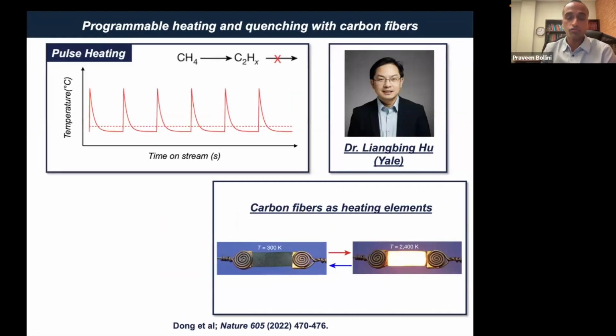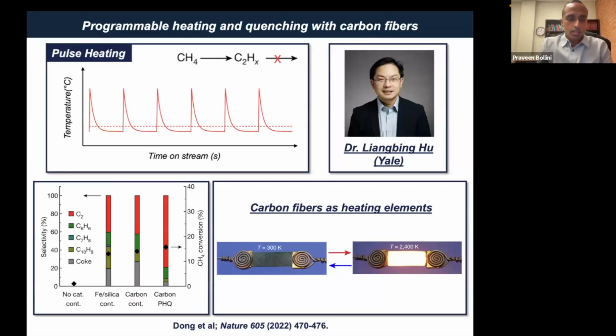And one of the very interesting things that Liangbing's group has been able to do is to use, again, dynamics, so to use a temperature program in order to obtain improved performance compared to just conventional steady state operation. And I'll just cite maybe one important data set here. So what you see is the selectivity to different products for different modes of operation.